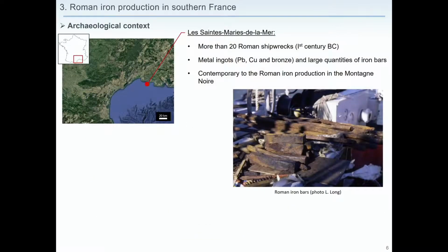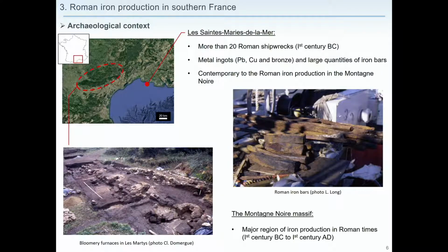We applied this approach to the provenance study of Roman bars found in shipwrecks near the French town of Les Saintes-Maries-de-la-Mer. In this town, more than 20 Roman shipwrecks have been found. They have been dated from the 1st century BC. They contain different types of metal ingots and large quantities of iron bars. They have been dated to the same period as a Roman iron production in the Montagne Noire, just there, where you can see here in the site of Les Martys a high concentration of remains of bloomery furnaces, which attests the importance of this region for iron production in Roman times, and in particular between the 1st century BC and the 1st century AD.